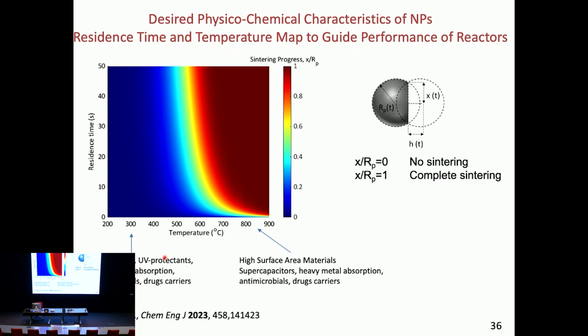And for a UV protectant, I might want an agglomerate. For an antimicrobial, I want an agglomerate. So I don't want sintering to proceed significantly. So as I increase the temperature, I go into a sintered state, which means it's collapsing into a single sphere. At a given temperature, as I increase the time, I also move into a sintered state.